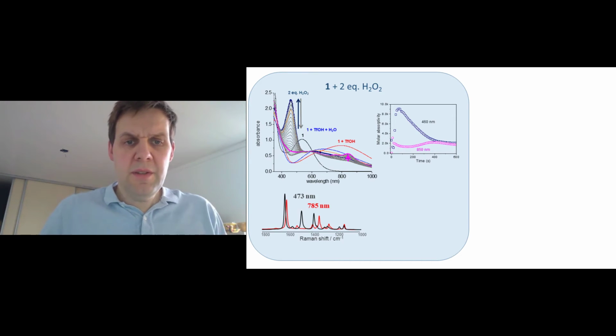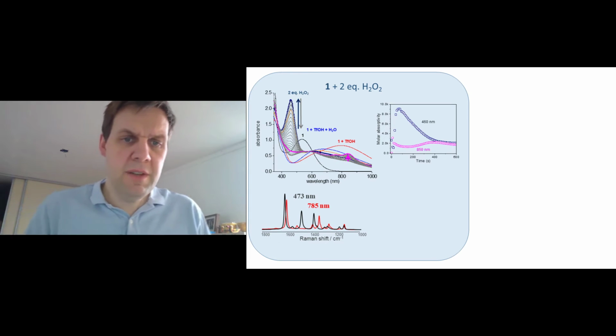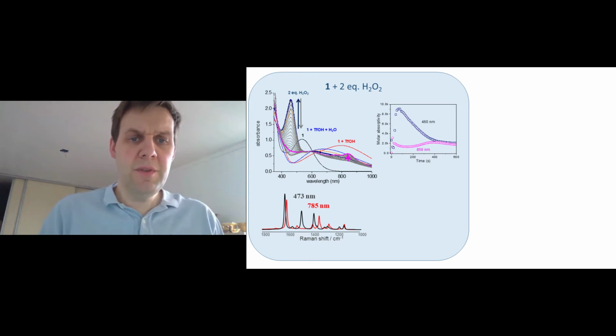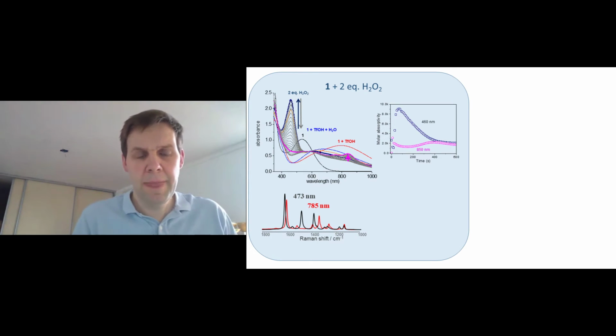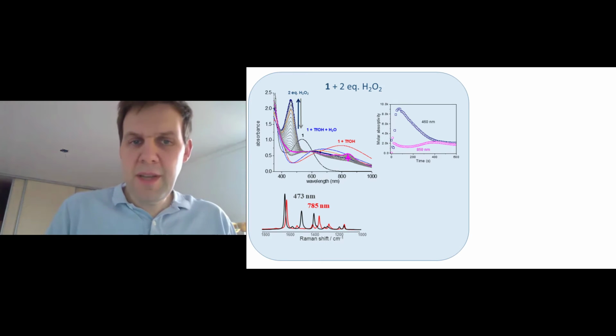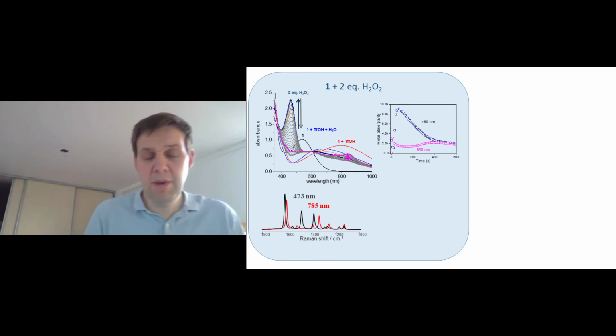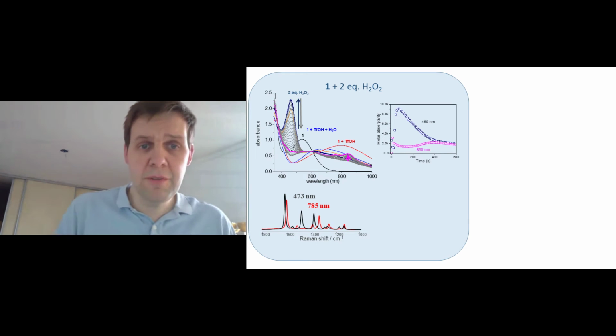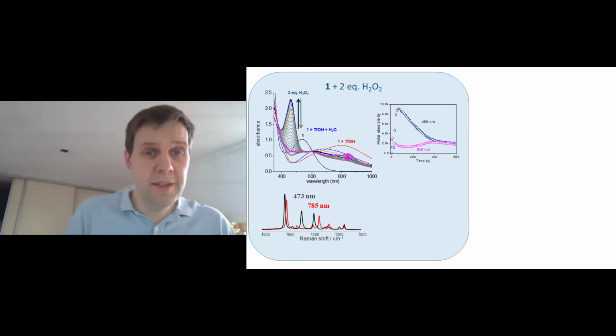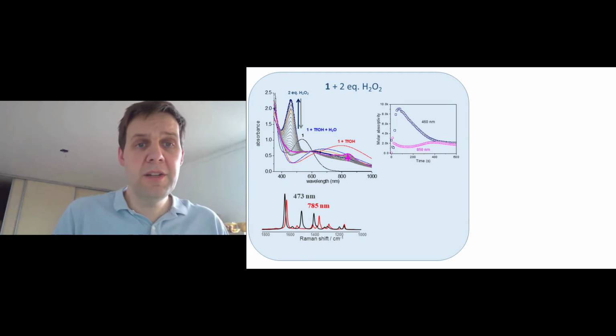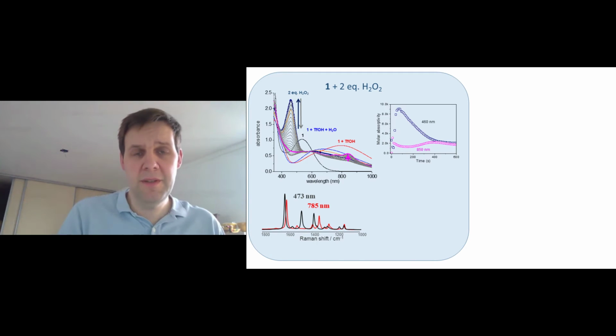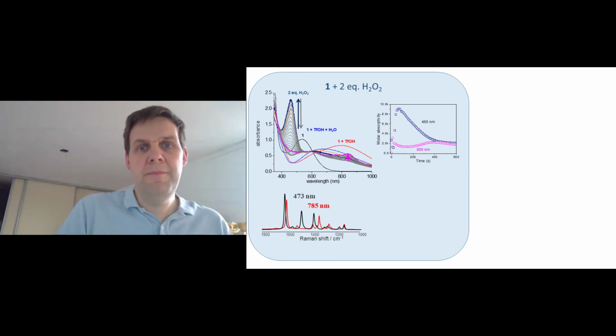And what we see is 2 very distinct spectra. At 785 and at 473, we see 2 spectra which are very similar, but similar doesn't mean the same. And a Raman spectrum is a manifestation of structure. So if the Raman spectrum is not the same, it's not the same species. So we are actually looking at 2 very similar but different species. Question is, what are they?